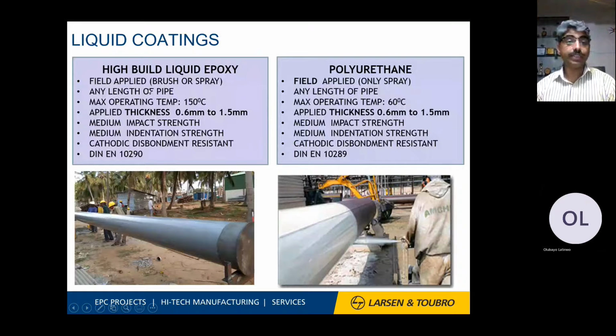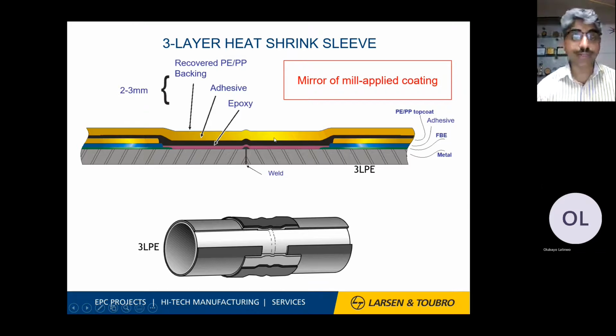Liquid coating, that is high build epoxy, liquid epoxy and polyurethane. The temperature for polyurethane is 60, whereas here it is 150, so it has high temperature applications. This can be applied by brush and spray, so it is easy to apply. This one is only by spray. Other parameters are almost the same for all, such as cathodic disbondment, impact and indentation properties.